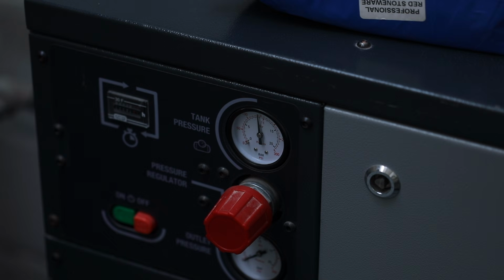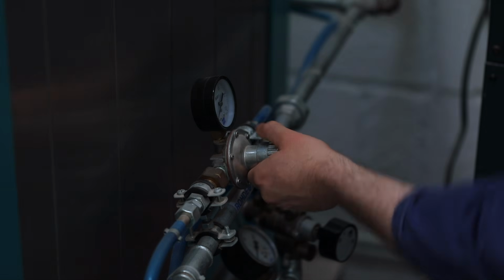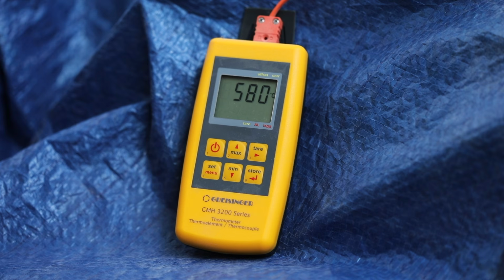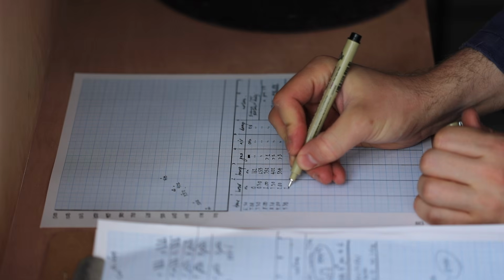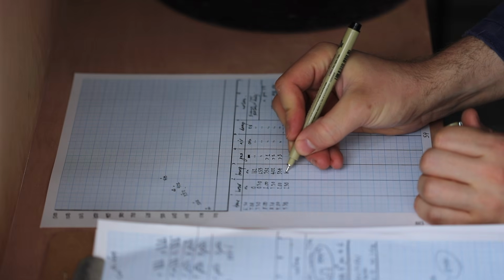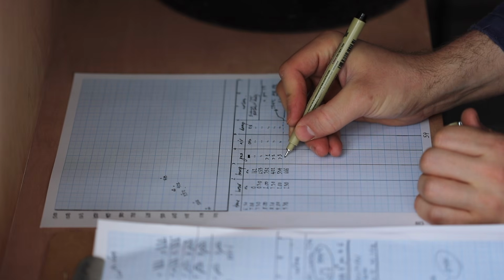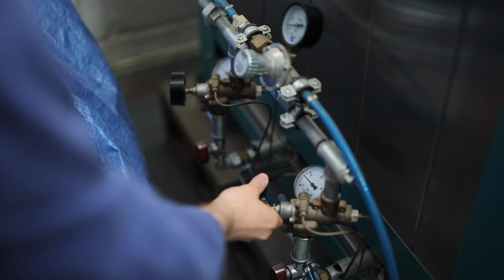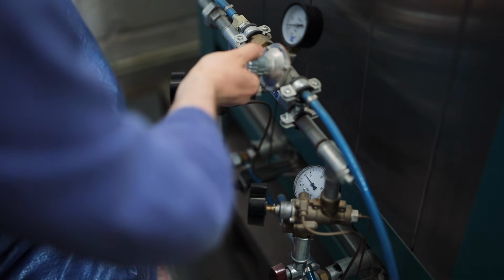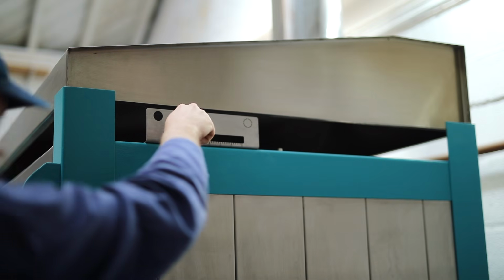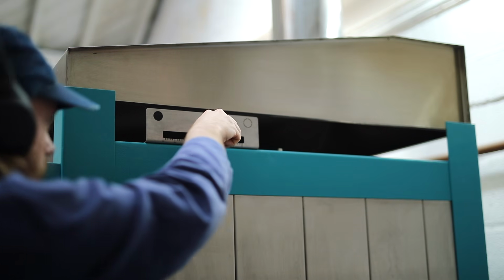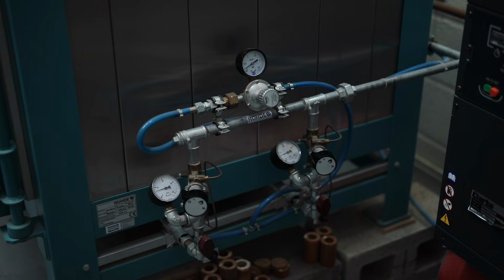It's horrible, isn't it? Despite this being one of the silent models that's sold. The good news is, at the start, it's not turned on much, as I don't need much air, but after reduction, which happens at 860 degrees precisely, it's turned up, and it tends to go off every 5 or 7 minutes. Speaking of reduction, to initiate this, I slide the damper to be half closed, and I dramatically increase the gas pressure and the air pressure.